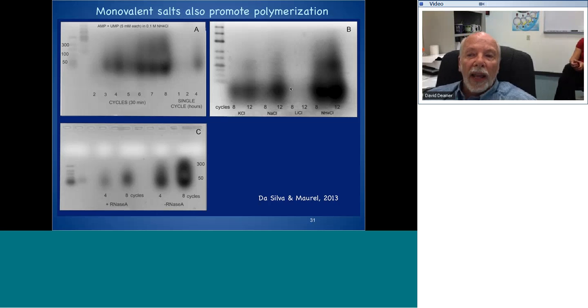For some reason we don't understand, ammonium chloride is the champion. We're getting up to 30% yield of polymers based on the original monomers present, whereas with the lipids, we were down to the 1% range. Very significantly, if you treat with RNase, whatever this polymer is, and here's one of these 4 and 8 cycles without RNase afterwards, you see the full 30, 40 mers and 300 mers. Look at that. The 300 mers are completely gone, and the 30 to 40 mers are largely hydrolyzed as well.